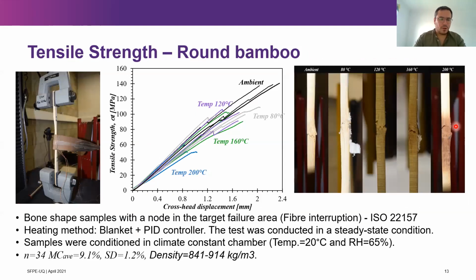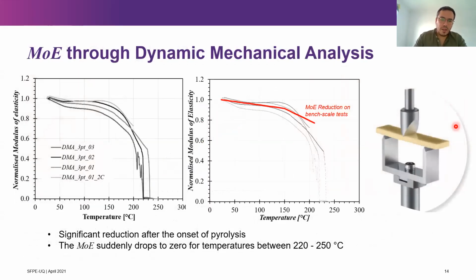We repeated the same process with the tensile strength. We conducted several tests at different temperatures, from ambient temperature around 20-25 degrees up to 200-250 degrees. Again, we measured the reduction in the modulus of elasticity and in the tensile strength. We performed some DMA, dynamic mechanical analysis, on small-scale samples, and we compared the results of the dynamic mechanical analysis against the results at the bench scale. What you can see here is the normalized modulus of elasticity against temperature.